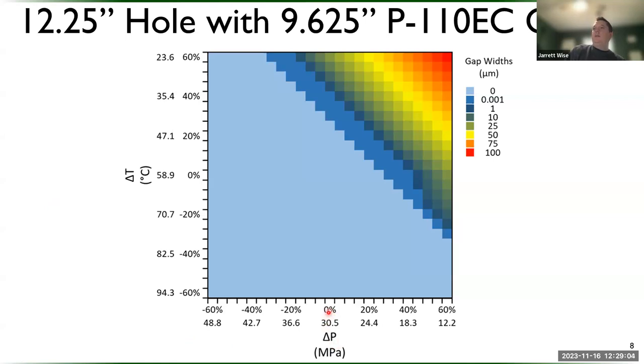Let me pull up my laser pointer. So what this assumes is if you have a wellbore and it was drilled at say 20 MPa mud weight or whatever, and then you produce the well and the drawdown pressure decreases enough over time, as indicated here, you can go from having a perfectly intact well to starting to get a microannulus between the cement and casing just based off your drawdown pressure. Same with temperature. If you drill it at some certain temperature and it has some sort of cycle, such as if you inject something in it or have geothermal, that can also cause microannuli to form. And we've shown that they can actually act together or counteract each other. So if you have a pressure drawdown, but no temperature change or the temperature does the opposite, it can negate each other. But if you have both at the same time, they can amplify.